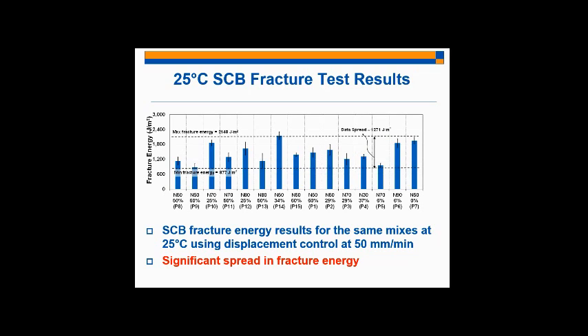So there's a significant data spread basically in these mixtures tested at 25 degrees Celsius. And so this was kind of a promising result that tells us basically that this temperature is better at distinguishing between these mixtures under the SCB testing condition. And again, these tests were run at the selected 50 millimeters per minute that I discussed earlier.